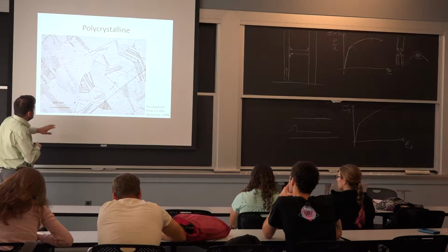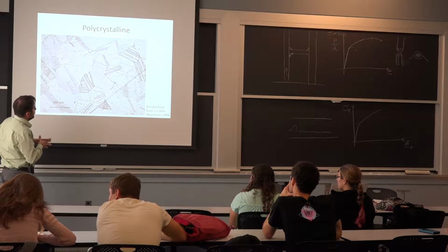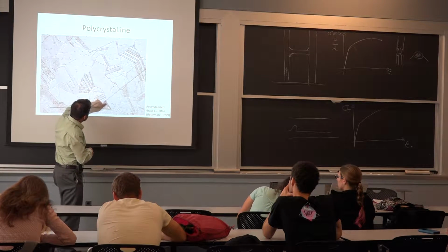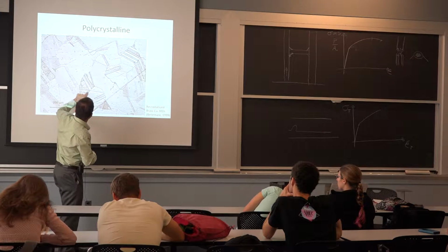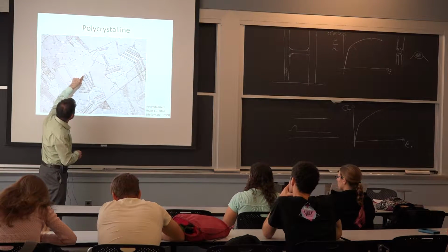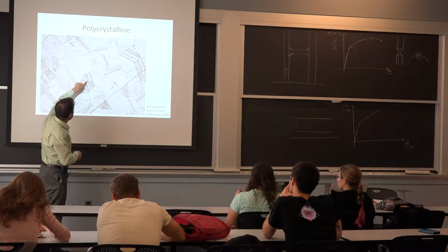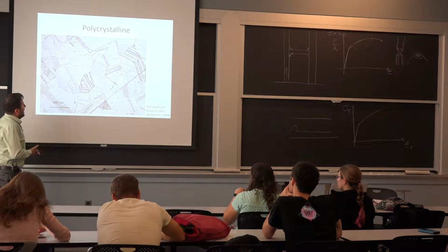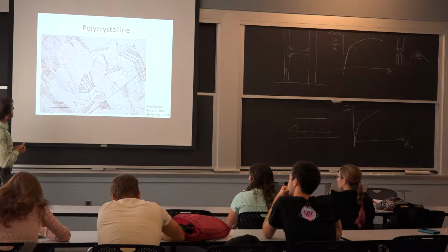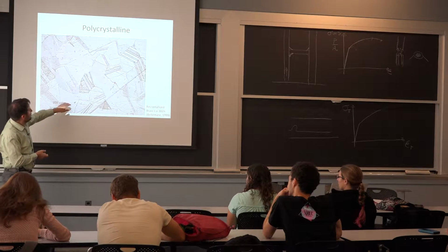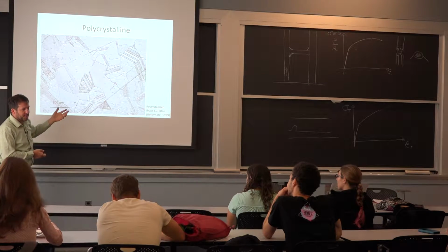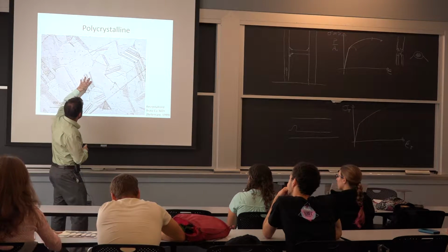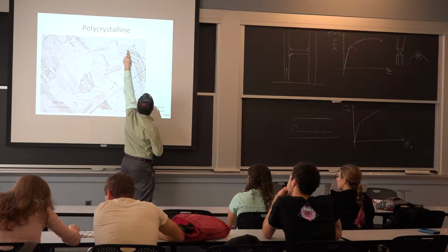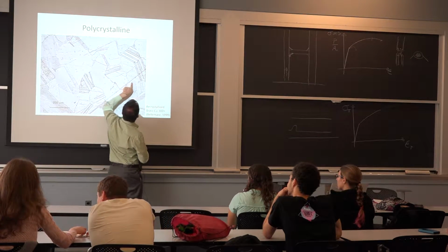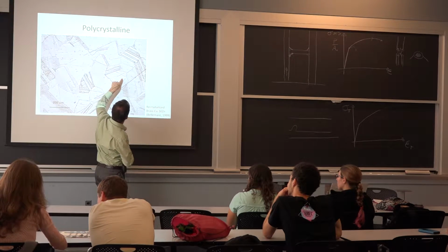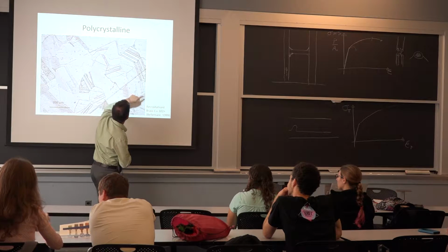So this particular case, we're looking here at a section of this before it was recrystallized at the high temperature. So this is the 400 degree. It's a very fine structure. You see the grains are these larger features. So you have one here, and inside the grain you just have twin boundaries. I think the good advantage is the twin boundaries allow us to see better the boundaries of the grain here. So we have one grain here that can easily be identified. We have one here. We definitely have, well, what is this line? I don't know, because the twin boundaries continue, so maybe this is a grain here.